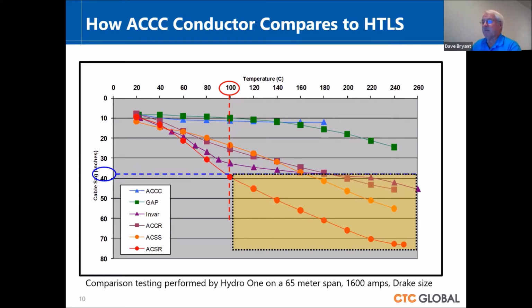If you look up at the green and the blue lines, you'll see these are GAP and ACCC conductors that both beat that sag criteria. The interesting thing, however, in the same group of HTLS conductors, in this case, the ACCC conductor ran 60 to 80 degrees C cooler than the other HTLS conductors. And that sort of underscores the improved efficiency.